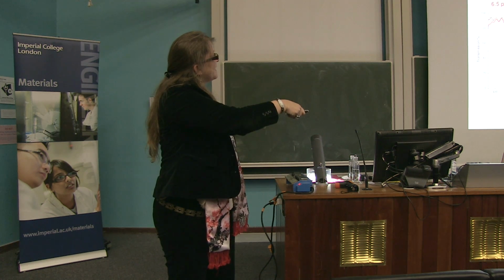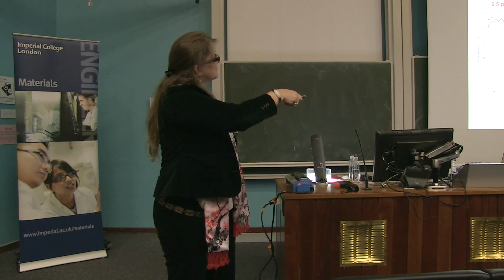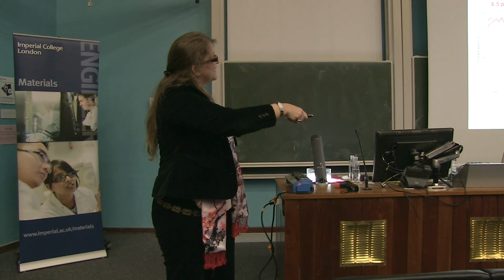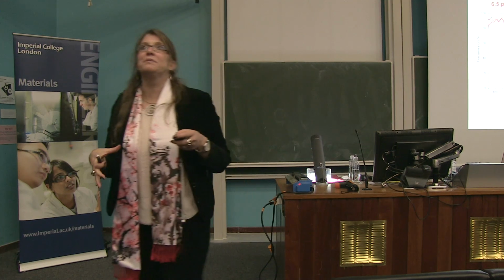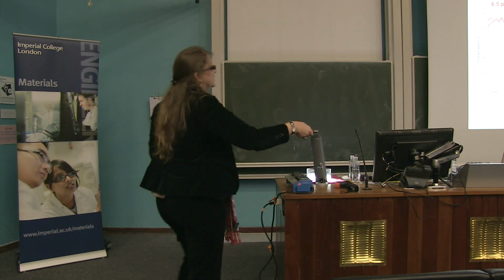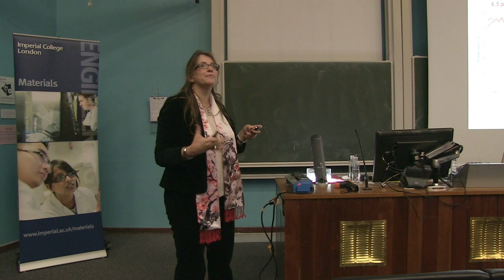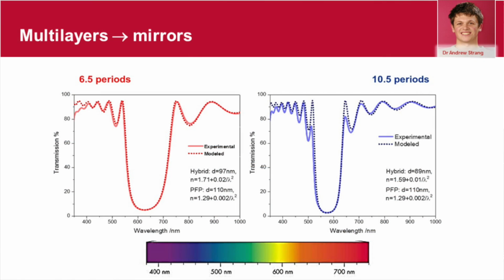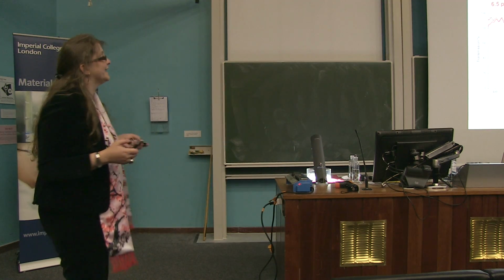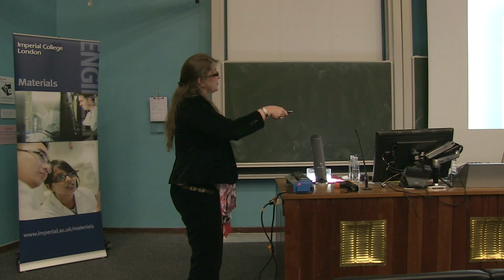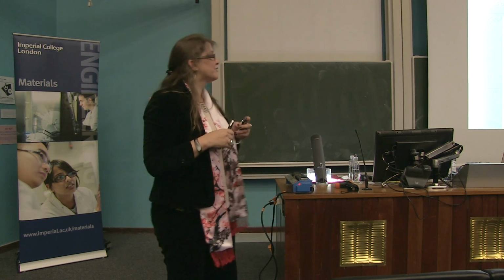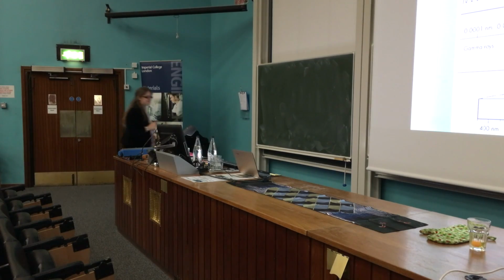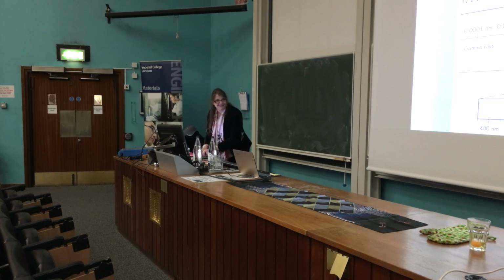But then you see, the more layers you have, the more you reflect. So here we have 13 layers, then we get to 21 layers. And here you get a system that is made with plastics, but at some given wavelength, reflects nearly all light. It's nearly a perfect mirror. And actually the color it reflects, you can tune by the thicknesses. So if in case we want to have purple reflected, we go to thinner layers. And if we want to go to a red being reflected, we go to thicker layers. And indeed, you can play this game even further. And then we can start to reflect infrared. And that's where my other experiment comes in, designed by Matt Dyson.